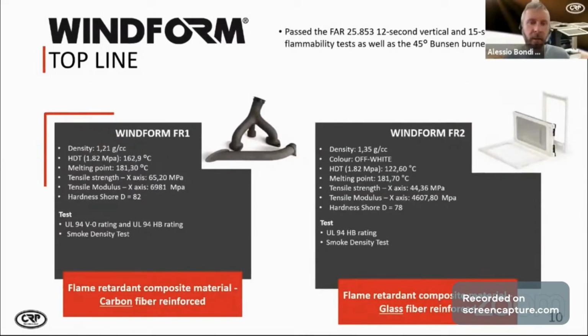Here we have the newest Windform flame retardant, FR1 and FR2. FR1 is rated according to UL 94, it's a V0 rating, and HB as well, and this passed also the smoke density test. As well as features of the material, we have a good density, it's 1.21 grams per cubic centimeter. A good HDT, 162 degrees, a melting point of 181. And here you can see the tensile strength and tensile modulus of 65 and 6,981 megapascal. The hardness shore is 82.